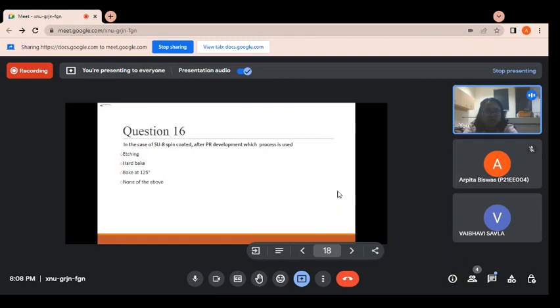Can you explain the total process flow for SU8? What is done after what process? So, ma'am, we have a silicon wafer. We first clean the silicon wafer. Once we get a cleaned silicon wafer, then we use the SU8 spin coater. Once the spin coating is done, we perform soft bake, which is at 65 degrees Celsius, and the time depends on the thickness of the SU8 material.